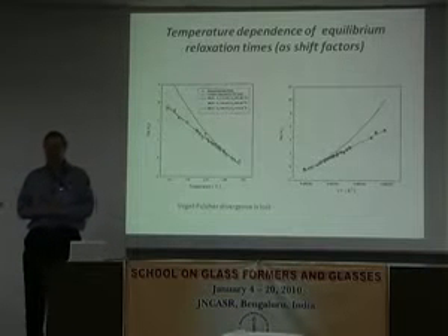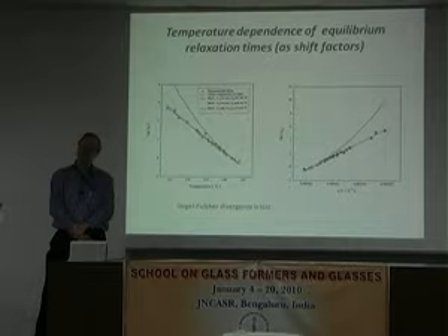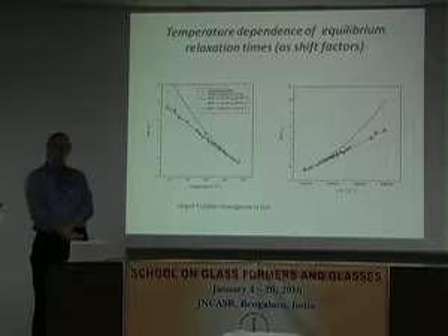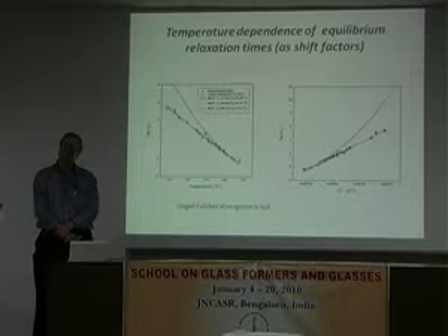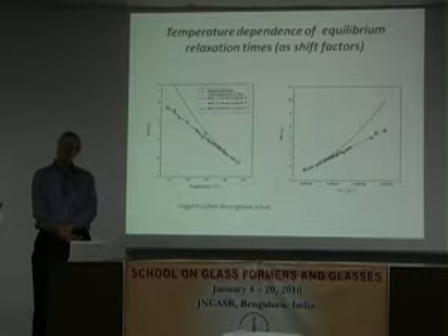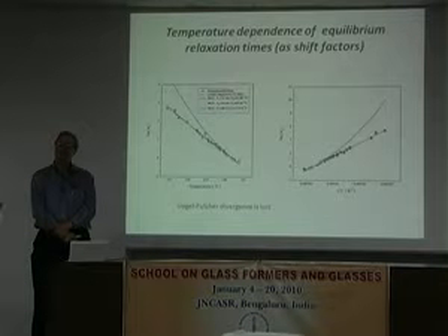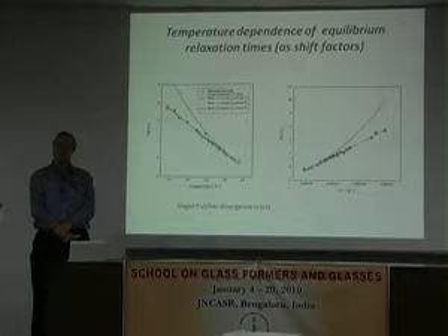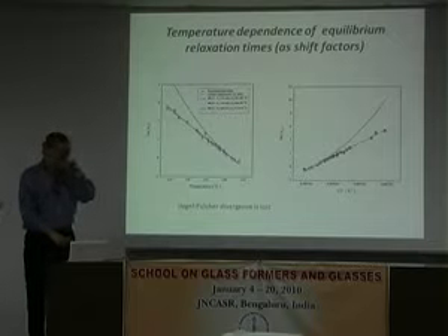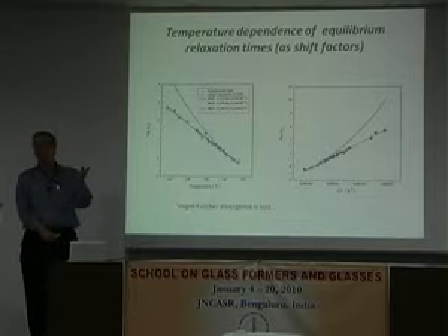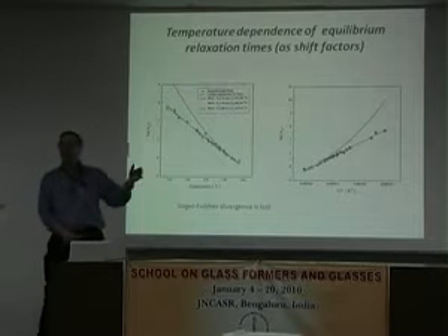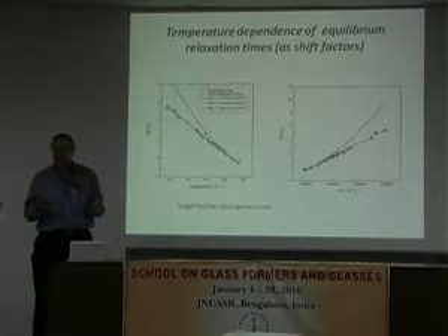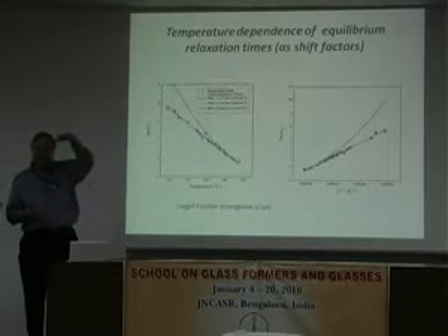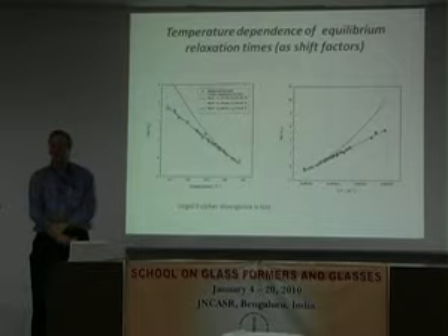Okay. Just one small question. Can we take this set of measurements as saying, look, why don't you forget about Vogel-Fulcher, do an Arrhenius plot, you will see a regime where it's not quite Arrhenius, and then eventually at low enough temperatures Arrhenius, and that is a better rendition of what's going on than saying that there's some Vogel-Fulcher and then there isn't. Well, you can do that, or you can do the Stickel plot. And the thing about the Stickel plot is it makes the Arrhenius regime a flat line. Okay, so then it's pretty clear, right?